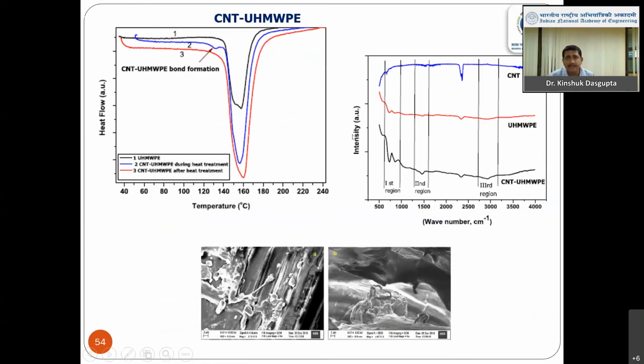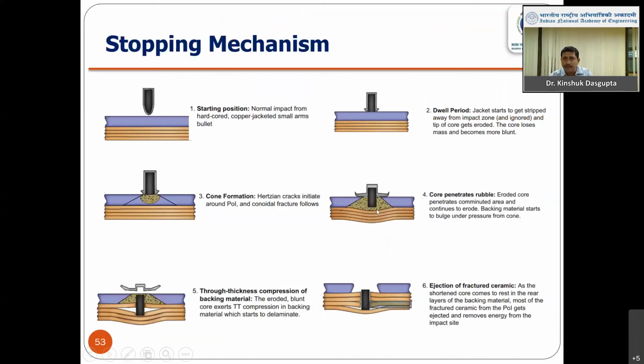Then how does carbon nanotube improve this? Here is a study we have done, called DSC, differential scanning calorimetry, which shows that the bond strength improves tremendously when carbon nanotube is used, and that is why much more energy is required to break them. Due to that, you end up with a low level of trauma. That means more energy is wasted here, so it cannot penetrate much, and your trauma is reduced. Second, when you improve the fracture toughness, energy is also wasted here. So you can use a smaller thickness of tiles and a smaller number of layers. In this way, you can reduce the weight of the jacket.